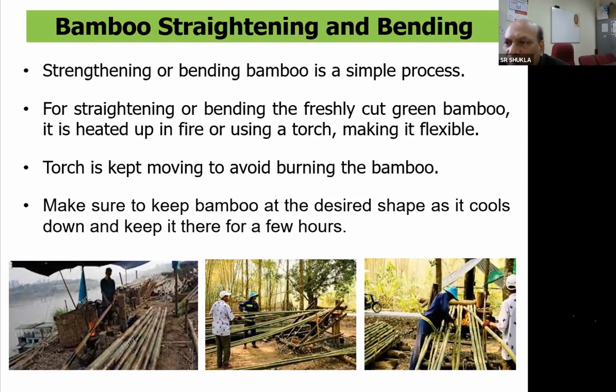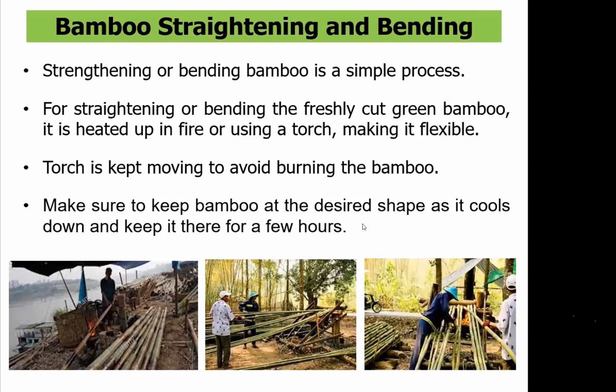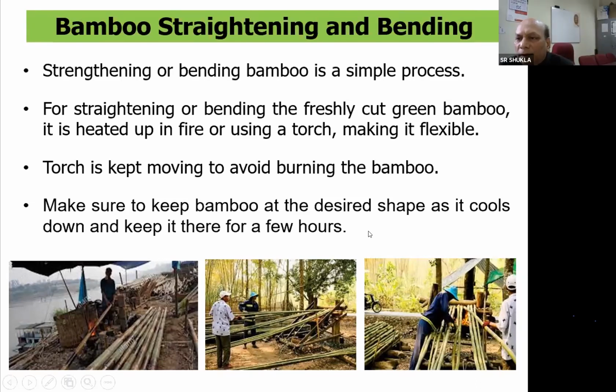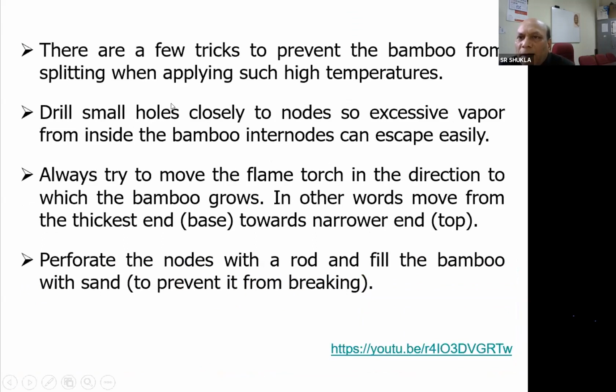Either it should be straightened or it should be bent, and it cools down and keeps it there for a few hours, so that it retakes the shape in that position. And there are a few tricks to prevent the bamboo from splitting when such high temperatures are applied. Like we can drill small holes close to the nodes, so that excessive vapors like water vapors will not get stagnated inside the bamboo, so that they will get released, and bamboo cracks will not develop in the bamboo columns.